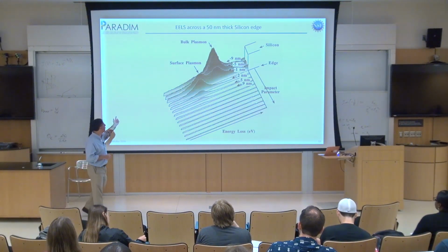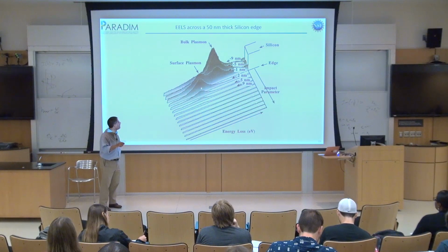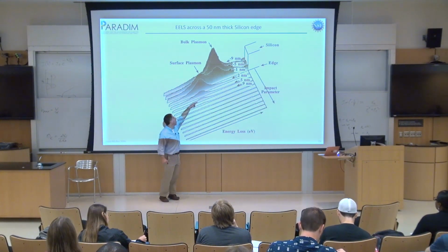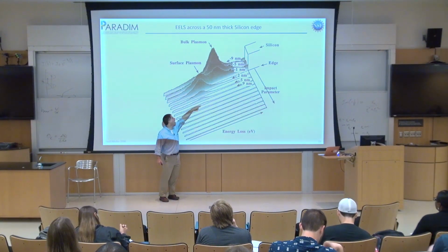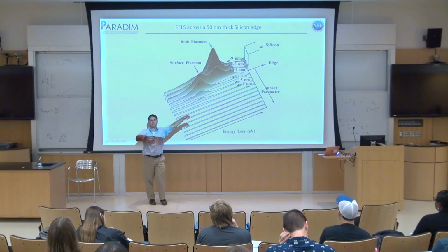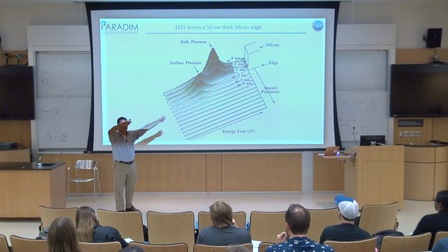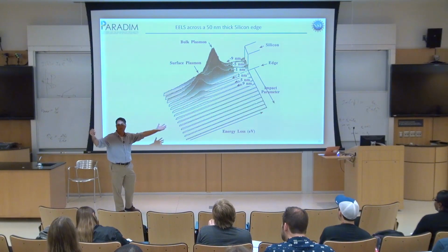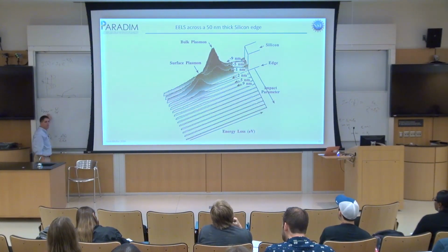Surface plasmon, 1 over root 2 of the bulk frequency. Here it is down in energy by 1 over root 2. And you can see it's coming up exponentially as I approach the interface. So you can still pick up the bulk plasmon 10, 15 nanometers into vacuum. Right? So here I am outside the material, and I'm exciting electrons inside the material because I create an image charge from the polarization with my electron beam, and my electron beam produced this nice electric field, which is long range and stretches out to a distance v over omega.